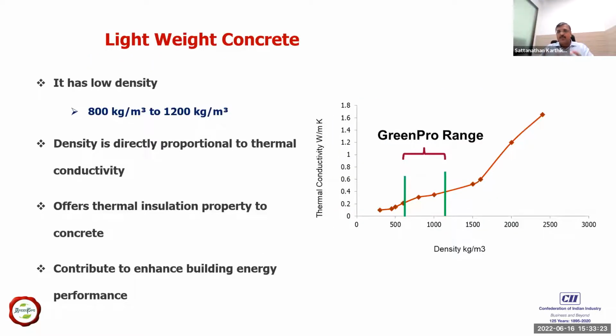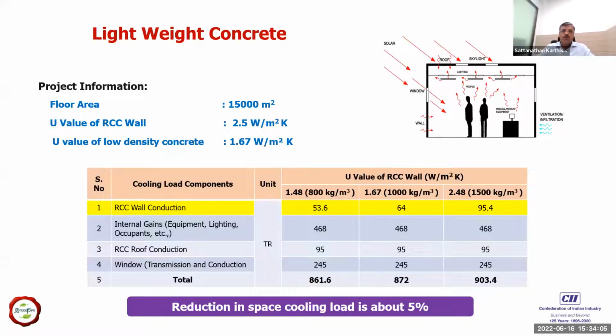And the second aspect is, for example, a lightweight concrete mixture not only reduces the carbon footprint of the building, it also improves the thermal insulation property of the building. This lightweight concrete has a very low density, anywhere between say 800 kg/m³ to 1200 kg/m³. And at this stage, the thermal conductivity, or the U value, is much better compared to a conventional concrete. So when the thermal insulation property is much better, obviously the heat gain in the building will come down. If the heat gain in the building comes down, you will also be able to reduce the air conditioning load and hence the energy consumption in the building.